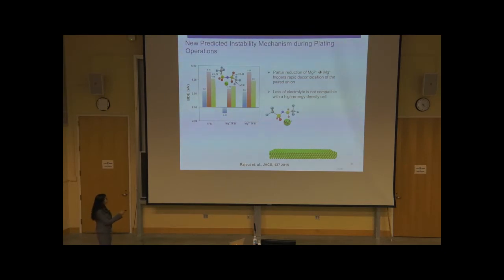So what's basically happening here is that this ion pair undergoes a partial reduction by taking an electron from the electrode, and magnesium 2+ is reduced to magnesium 1+, and this process activates the anion and makes it susceptible to decomposition. And it could be really bad for a battery because it will result in loss of electrolyte through an irreversible reaction and possible deposition of this decomposed product on the surface, which leads to the formation of a blocking layer at the magnesium metal anode.